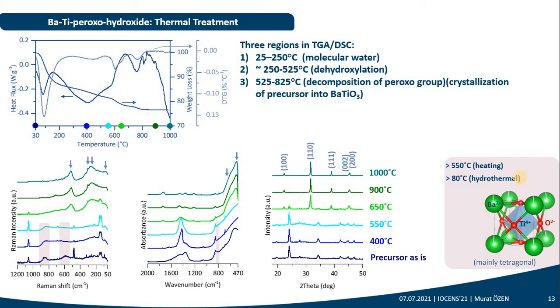The precursor material was also thermally analyzed by TGA-DSC. The TGA-DSC graph is shown here, and the Raman, infrared, and XRD results are shown here below. The Raman, infrared and XRD results are of precursor materials which were treated at 400, 550, 650, 900, and 1000 degrees Celsius. When we analyze all of these results, we see that, first of all, the thermal analysis shows that